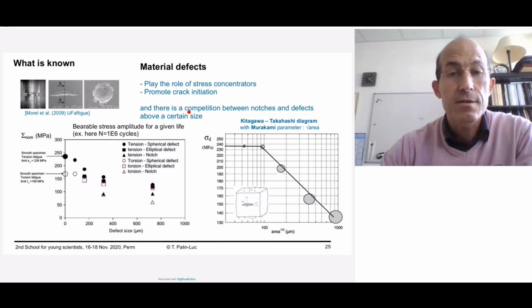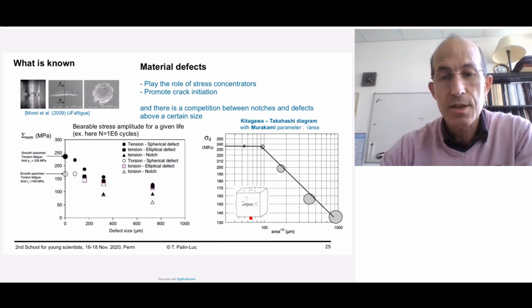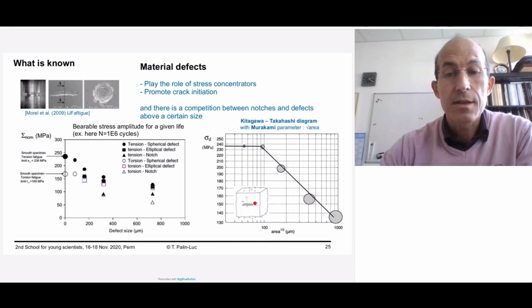So this competition is very well illustrated in a famous Kitagawa-Takahashi diagram, which is the illustration in the vertical axis of the fatigue resistance versus the square root area of the defects. So you imagine that you are loading a material volume with the defects here. You are loading this in tension under cyclic loading, and the projection of the area of the defects gives you the critical defect size, which is computed by the square root area of the projection of these defects.